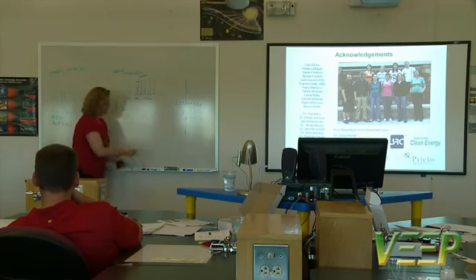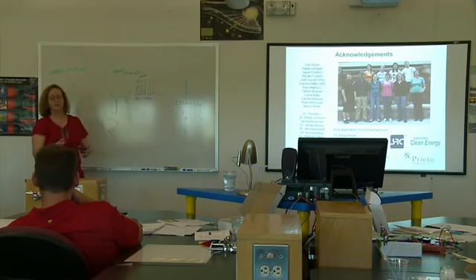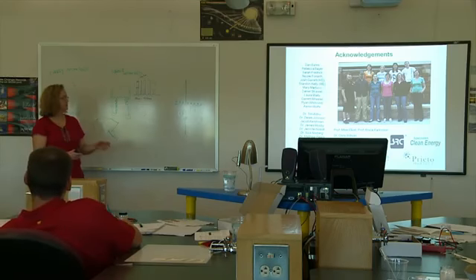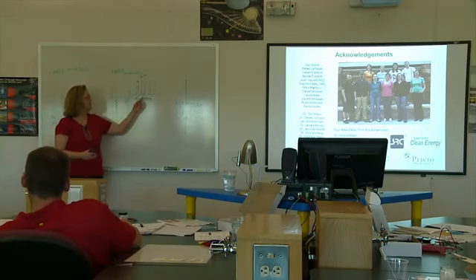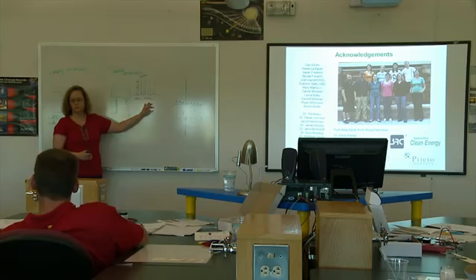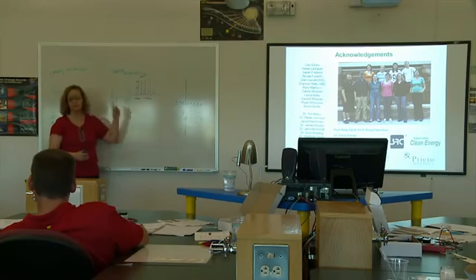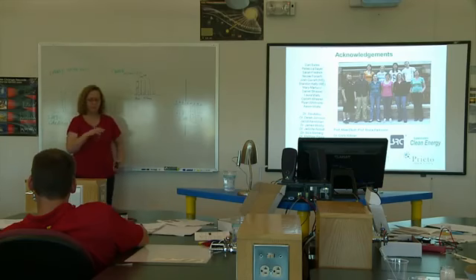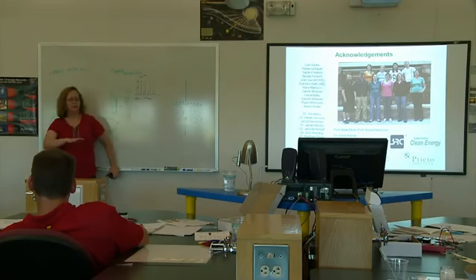This nanowire array, it's 10,000 times higher than that. So on the 45 nanometer diameter wires, you can fit about 10,000 in the width of a human hair. We grow them ourselves, and the way we do it is we start with a piece of aluminum metal, and if you oxidize it in an acidic solution, it's called anodization, you grow this amazing structure of holes that grow straight down, they don't ever intersect, and you control the diameter of them and their spacing.